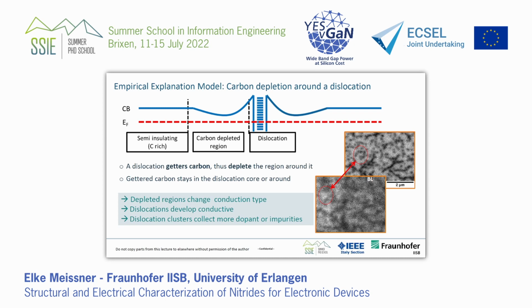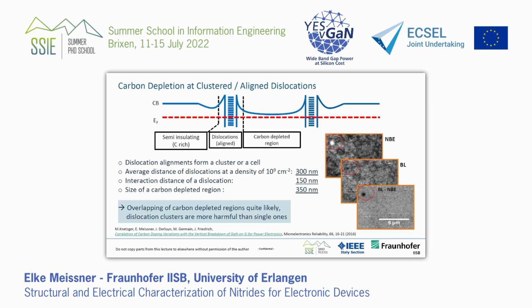Whereas you should have a semi-insulating material all over the device area, which you don't have. So this is what we found from this analysis. And if you have more dislocations, you can even deeper deplete it, because in the middle between dislocations, you find that there's even less carbon. So now you can compare it with average distances of dislocations at certain dislocation density.